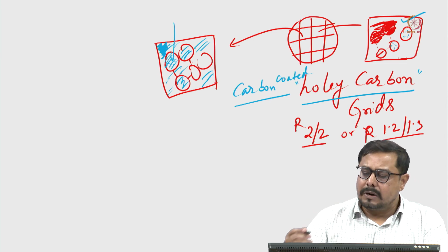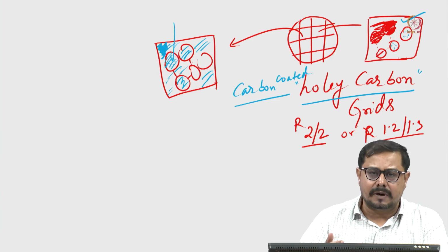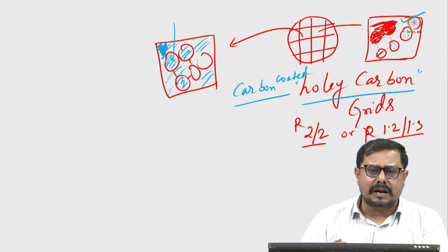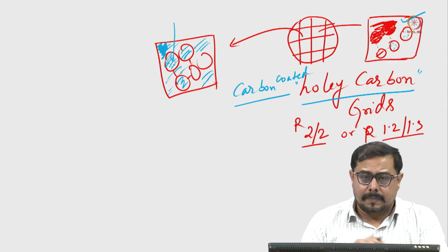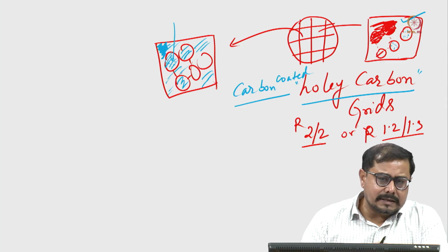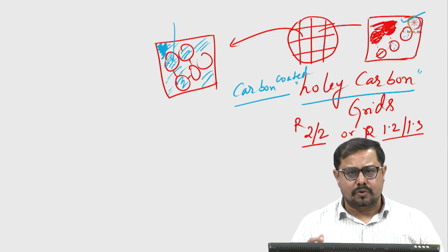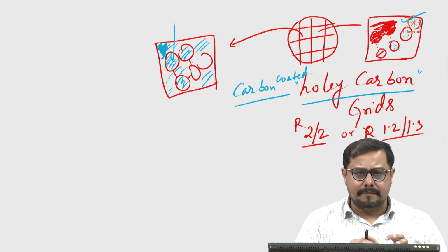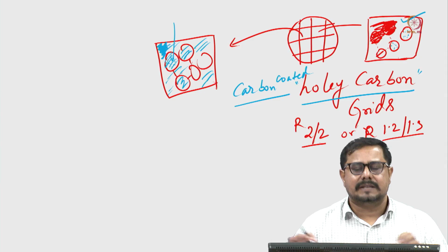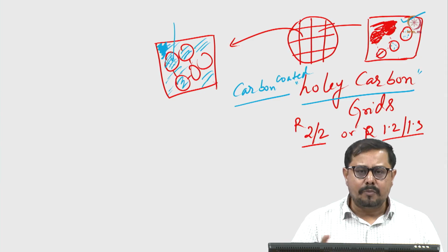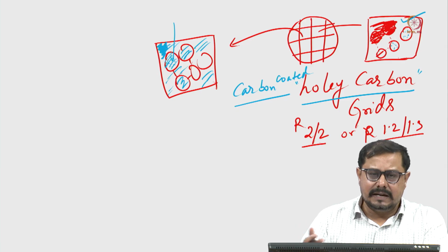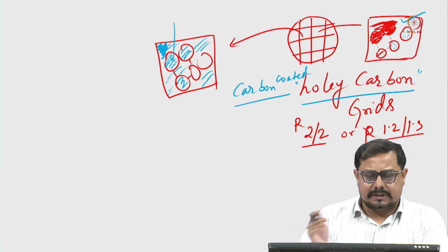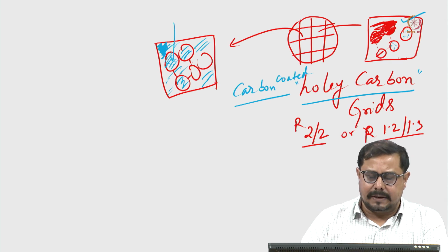Also you have to remember, whenever we are using different types of grid, whether continuous carbon coated grid, holey carbon grid, carbon coated holey carbon grid, or graphene coated grid, in all cases how much glow discharge you have to do, there is no specific number of seconds that you can use. So sometimes you have to optimize those things. Whenever you change grids, it is better to optimize those parameters and then start freezing your sample.